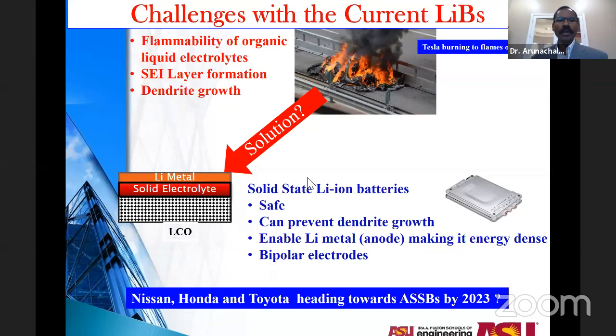So the major breakthrough is mainly with a solid electrolyte, if it really happens probably in the next decade or so. The solid electrolyte is one component which would act as an electrolyte and also separator. This material, being highly impervious to any material movement through it, excepting ionic movement of lithium, could lead to an extremely higher level of safety. And certainly, because of the extremely fine pore structure or absolutely no pore, it could also prevent dendrite growth.